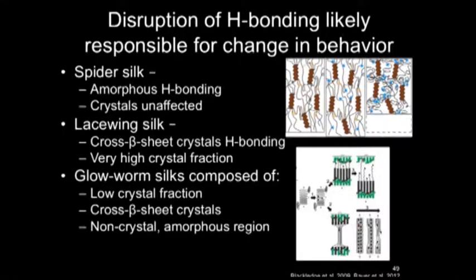Now, this is because at a molecular level, water disrupts hydrogen bonds that occur between the molecular lattice, so that when water penetrates the fiber when exposed to wet air, it disrupts these connections between the amorphous structures, those alpha helices, beta turns, and this allows for greater stretchability because these structures can then unfold rather than potentially being damaged as they're bound together.